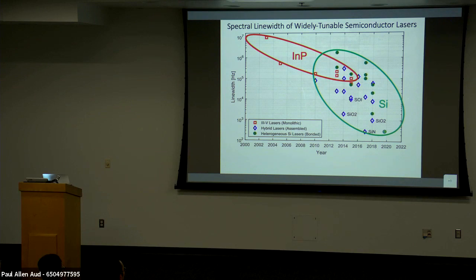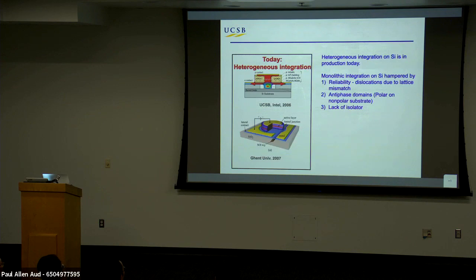It's exactly what you expect because the low loss gives you very high Q cavities, very low spontaneous emission noise. And so there's lots of groups that are doing this. And again, that's kind of inherent in the low loss of silicon, very high finesse cavities. So that's sort of heterogeneously what's going on in industry and some research results.